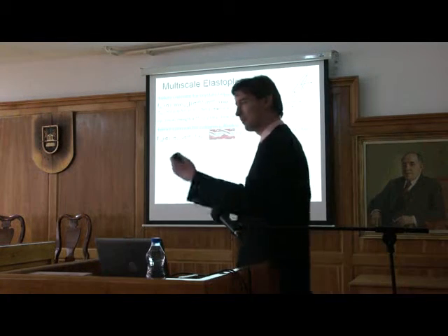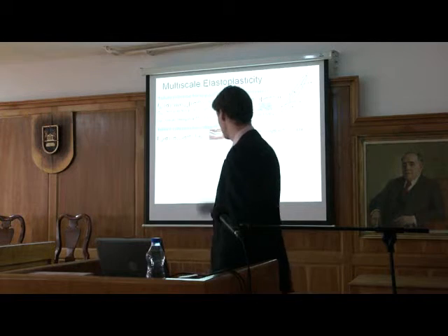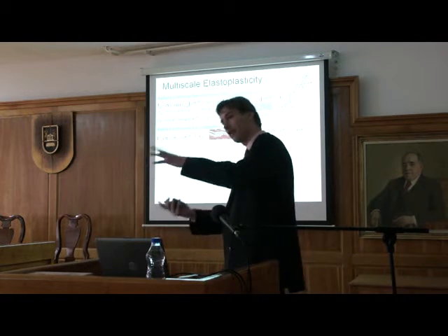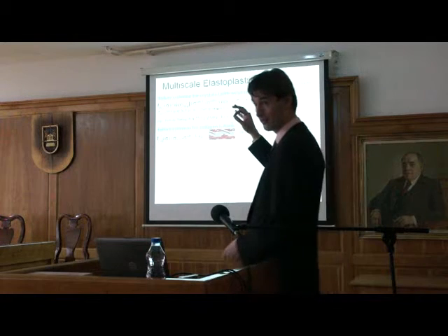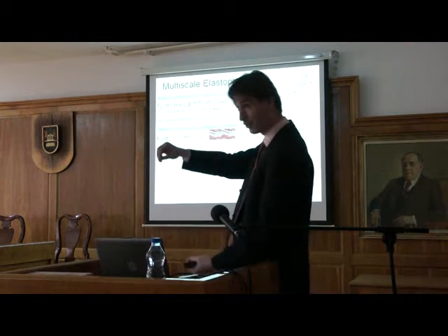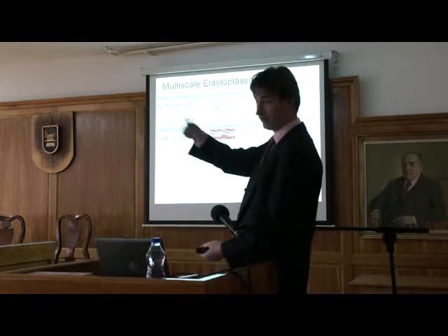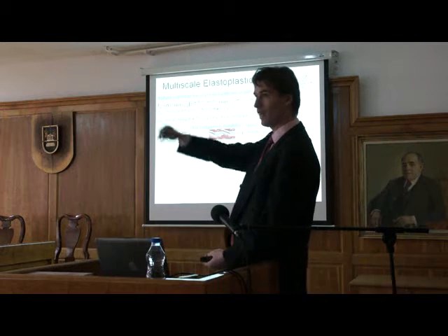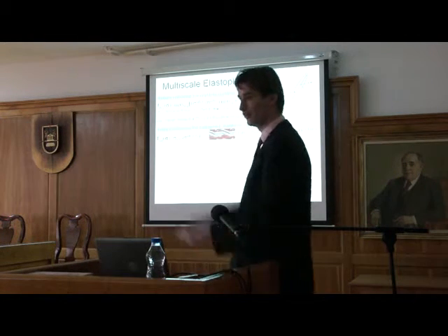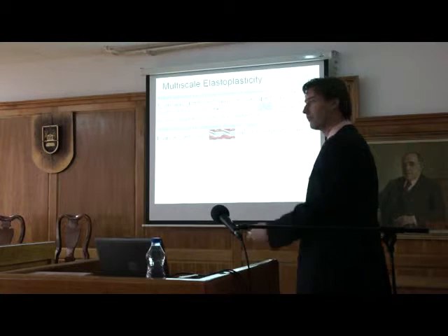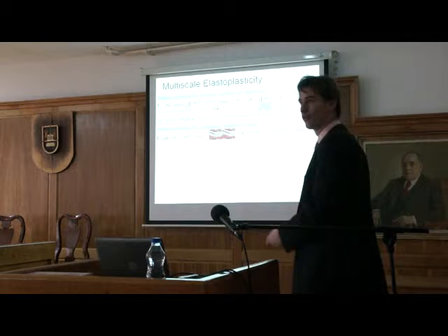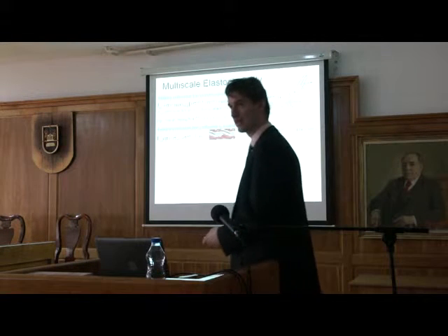Material speaking, a lot of people say, well, it's ductile and so on, but it's a consolidation problem. You have the water, you press out the water, but it has nothing to do with collagen strength. If you take a piece of collagen fiber, you make a direct strength test, you find a lot of papers on that. It goes up and then it's suddenly over. So we have a plastic mineral water system with a brittle collagen reinforcement. It's very close to reinforced concrete.